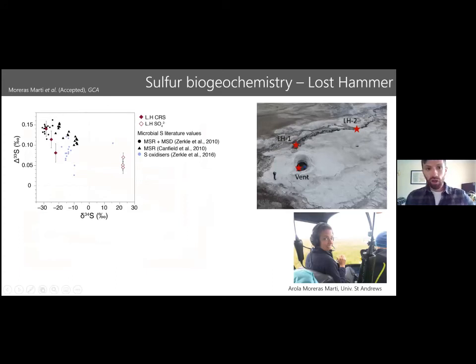So this establishes the analog and shows how useful it is for understanding the formation of Europa surface material. Now the question is what aspects of the biogeochemistry in this system we might expect to detect in the salts left behind in the deposits. This is Arola Moreras-Marti, a postdoc at St. Andrews. She's been doing fantastic work looking at sulfur biogeochemistry. These systems are known to be dominated by sulfur cycling organisms, and evidence for that can be seen in the precipitates that are formed. Arola extracted the sulfates and sulfides from three different locations on the Lost Hammer spring. These represent a gradient of oxidation, from the anoxic fluids delivered to the surface to the more oxidized downstream locations represented in the upper right-hand image.